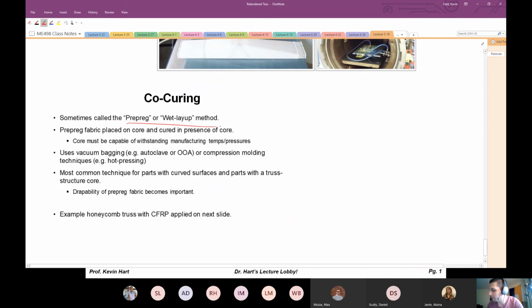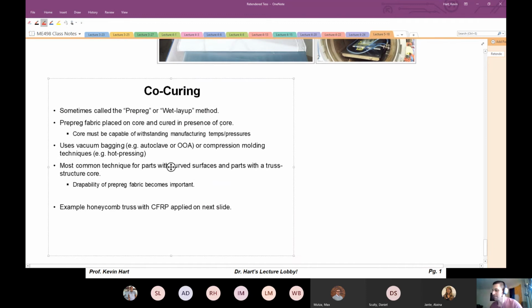Sometimes it's called the pre-preg or wet layup method, obviously, because you're applying pre-preg or wet fabric right to the core material, and the pre-preg is placed on the core and cured in presence of the core, which must be capable of withstanding manufacturing temperatures and pressures. So if I wanted to use a PLA core material, I'm going to have a bad time if I'm bringing that up to temperatures of like 100 C. The glass transition temperature of PLA, for those of you with polymer background, is about 50 degrees Celsius. If I take a PLA core and expose that to 100 degrees Celsius, that thing isn't going to last.